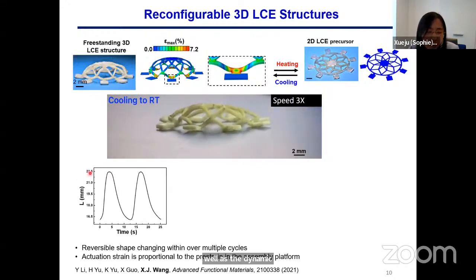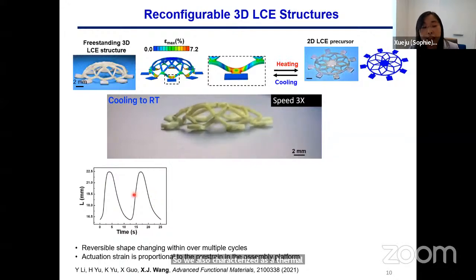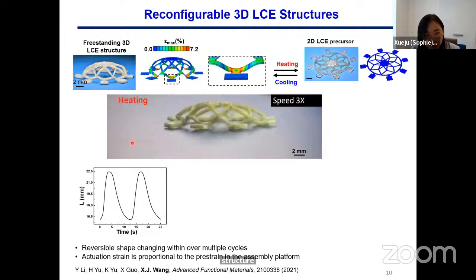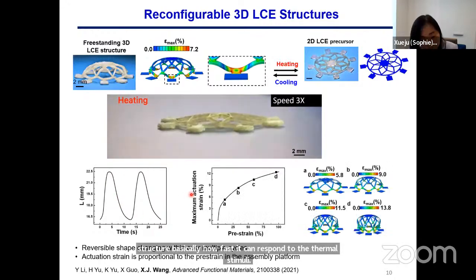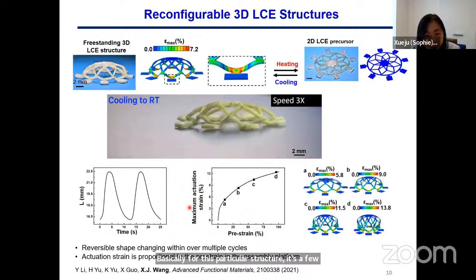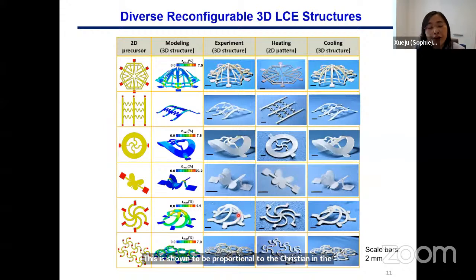So we also characterized the thermal response of the structure, basically how fast it can respond to the thermal stimuli. Basically for this particular structure, it's a few seconds. And we also characterized the maximum actuation strain of the structure, which is shown to be proportional to the pre-strain in the assembly platform. So here are a series of experimental and simulation results of the 3D LCE structures enabled by this technique, including those that can mimic, for example, a butterfly and a cage, and also we presented their reversible shape morphing behavior. Basically, you can see the 2D pattern and the 3D structure after heating and cooling.